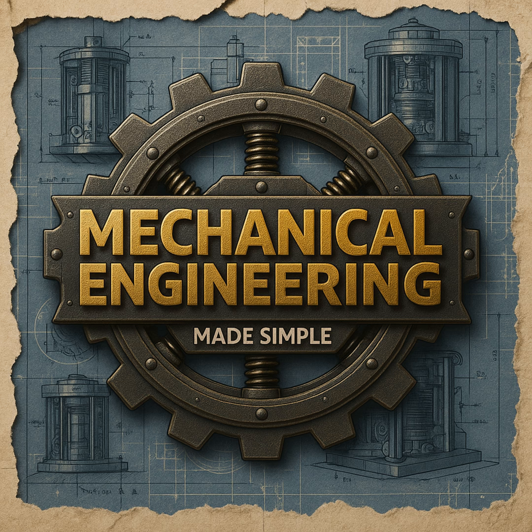Yes, it is. But eventually it hits tertiary creep. The internal microstructure of the metal literally begins to break down. Microscopic voids form at the grain boundaries. Oh, wow. So the remaining cross-section actually shrinks. Exactly. The strain rate accelerates rapidly, and the part inevitably pulls apart in a catastrophic failure called stress rupture.